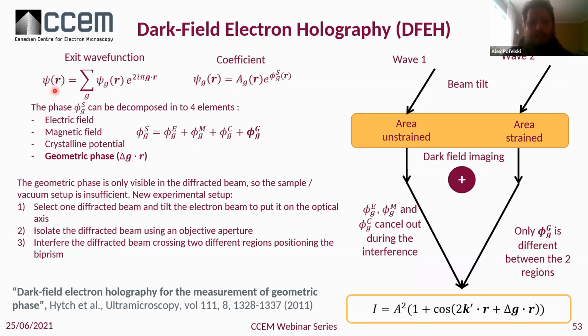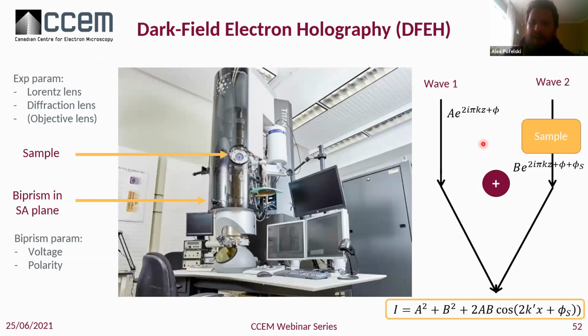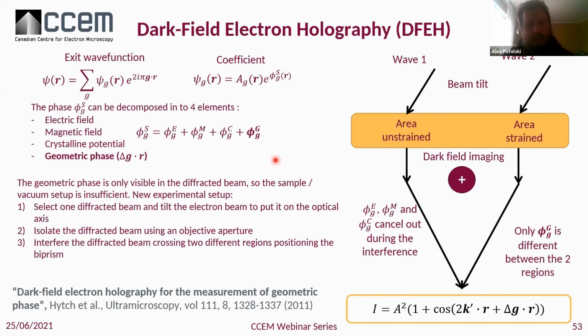So I won't go into the detail, just for the sake of time. I'm just going to speed up a little bit. But what I just want to mention here is that what we are interested in regarding strain is the geometric phase. And I recommend actually to read that paper if you want more detail about this. The geometric phase is only visible in the diffracted beam. So this setup here is kind of insufficient, especially if you look at the primary beam. So we need to tweak this a little bit differently to be able to see this geometric phase.